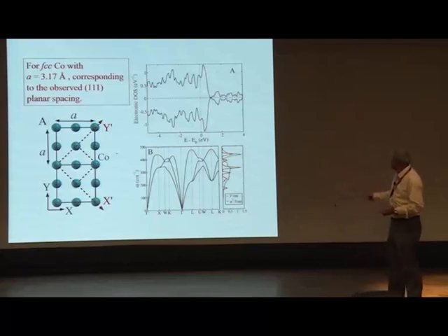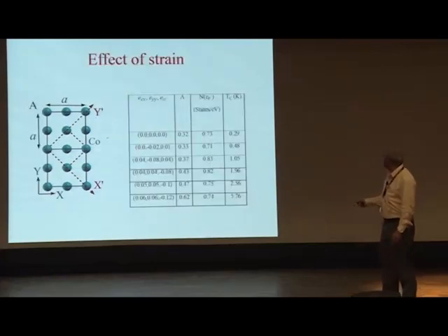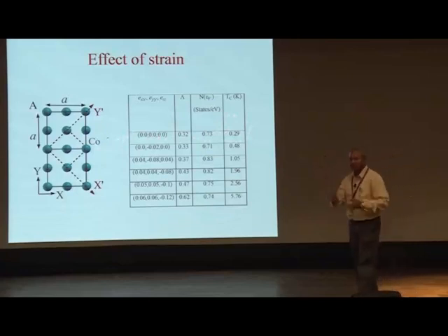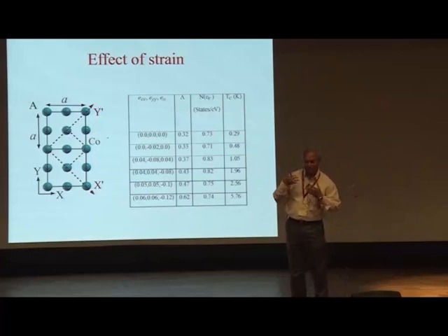This is non-magnetic, and this is the phonon dispersion, and the green one is the phonon density of states, and the red one is called the Eliashberg spectral function that is used in the calculation. So if you do all this, you find your TC is about 0.3 Kelvin. But this is FCC, just a uniform contraction. In a thin film, you never expect a uniform contraction. You expect anisotropic contraction, so you introduce a strain in the calculation.